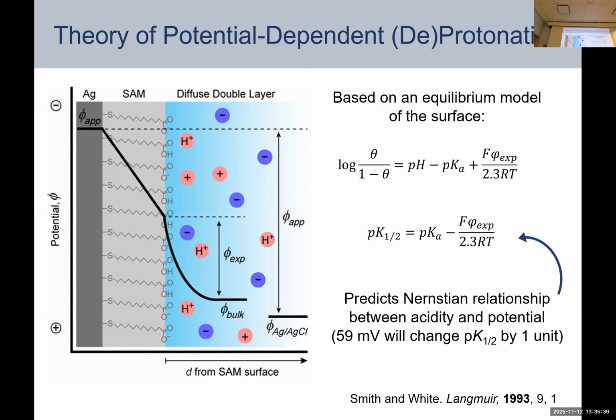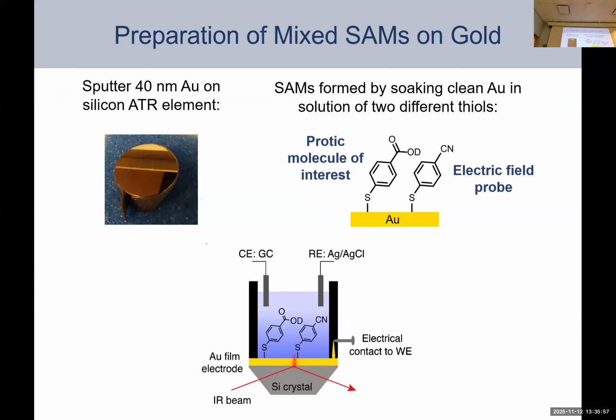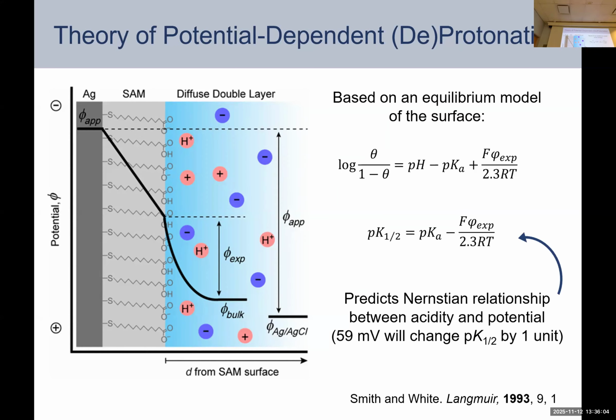Okay, so here's this familiar term for electrochemists, 2.3 RT. So we expect that for every change in the applied potential or experienced potential, we should see a change of 1 unit in pKa, 59 millivolts. Okay. So we were curious to see whether that would actually pan out with a molecular adsorbate where you have, sorry, let me go back for a second, where you have this large drop in applied potential through the organic piece of your self-assembled monolayer.